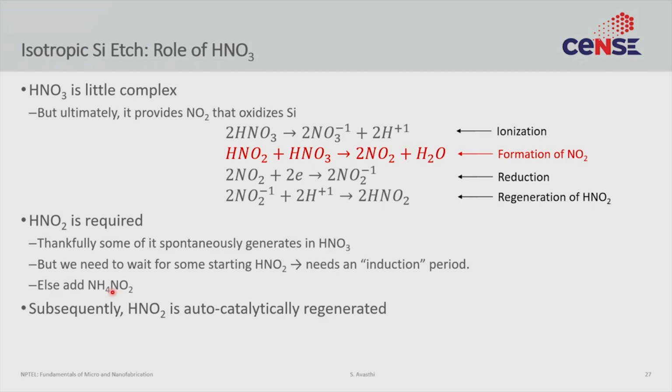Okay? So, I think this is called ammonium nitrite. And what this does is it provides you with the NO2 minus immediately without you needing to regenerate it, and thereby avoid the induction period completely.